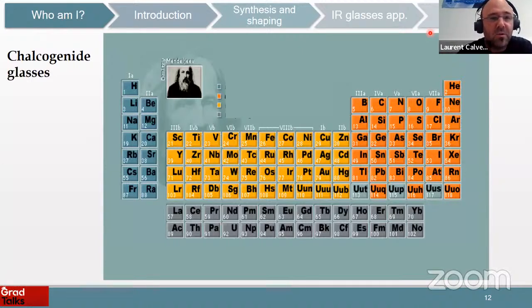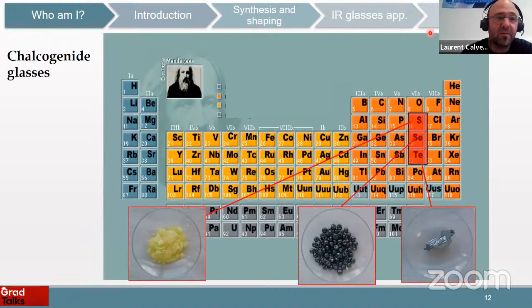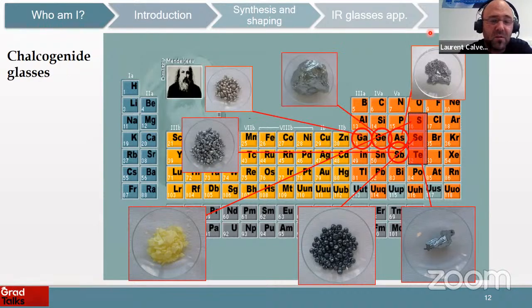So chalcogenide glasses are based on different elements. What are the chalcogenide elements? Sulfur, selenium, and tellurium. But it's very difficult to make glasses with only these elements. So you have to add other elements, very heavy elements like gallium, germanium, arsenic, and antimony. As you can see, arsenic and antimony are not so friendly elements, but they are good to make this kind of glass.